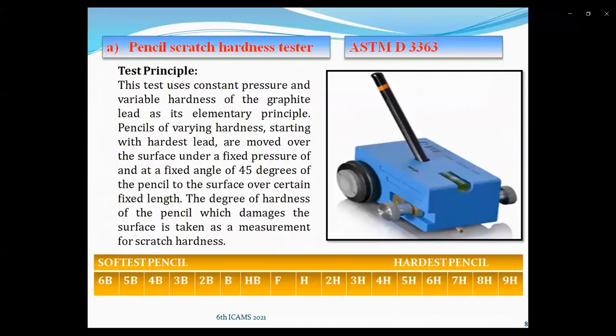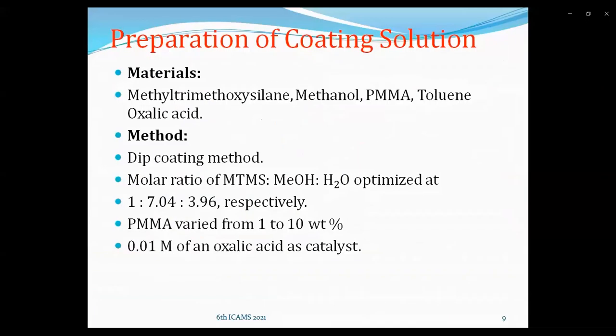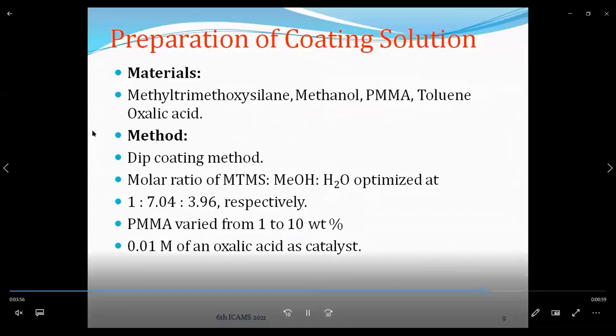At the bottom, you have the softest pencil grade to the hardest pencil grade; it varies from 6B to 9H. Preparation of coating solution: materials used were MTMS, methyltrimethoxysilane, methanol, polymethyl methacrylate, toluene, oxalic acid, etc. Dip coating method was used. The molar ratio of MTMS, MeOH, H2O was optimized at 1:7.04:3.96 respectively, and PMMA varied from 1 to 10 weight percent with 0.01 molar oxalic acid catalyst.